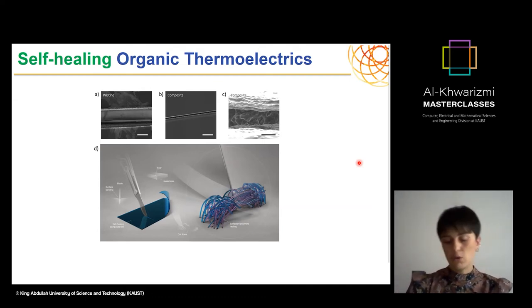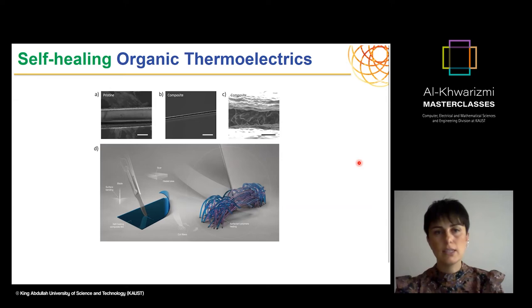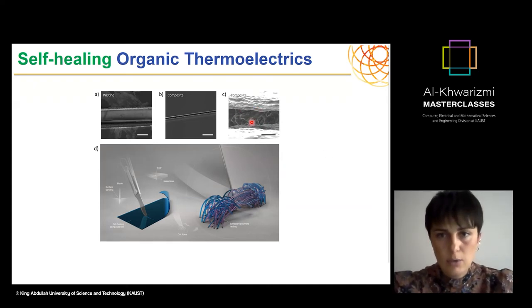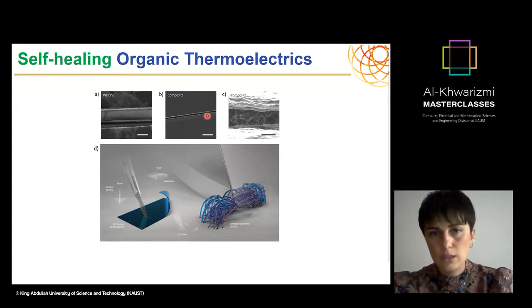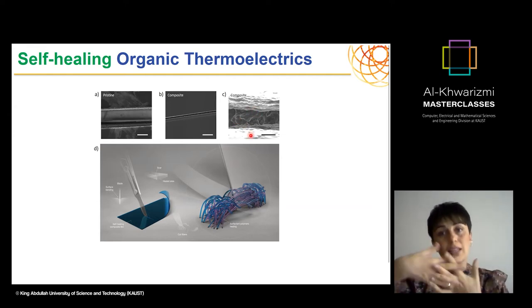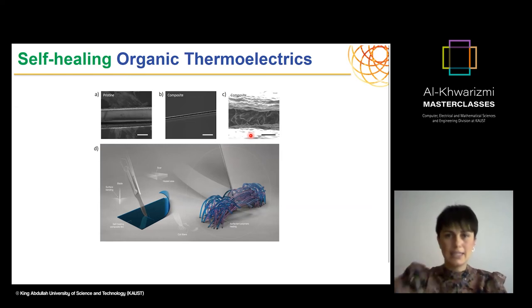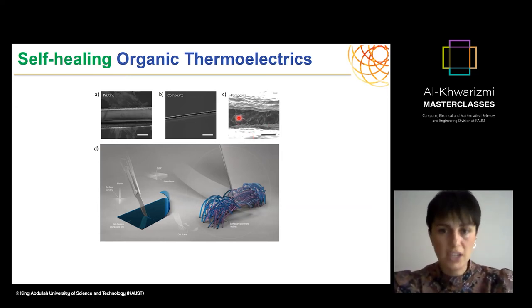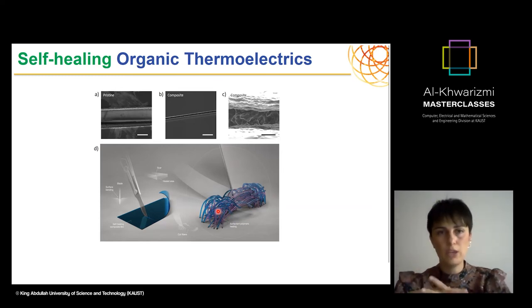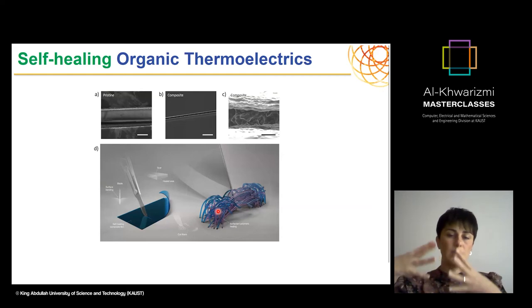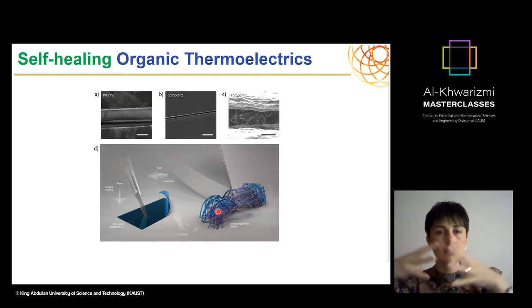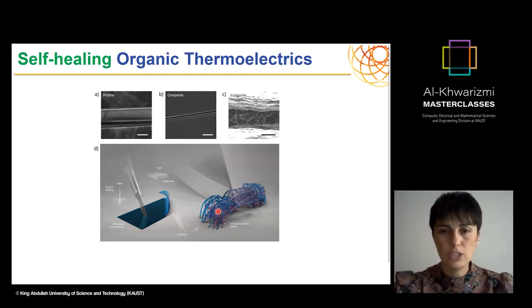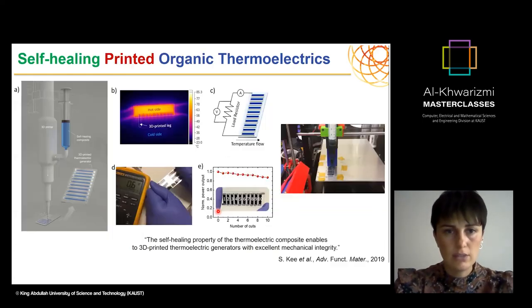And then we used some commercially available materials to start with. And in the end, here you see some of the SEM images. We had a huge cut and then looked into that. And we were still able to see that the self-healing material was in there, healed, let's say, and functioning. So this is our hypothesis that the self-healing material is bundled with the PEDOT molecule. And when you cut it, it supposedly heals back and then makes those polymer chains closer to each other again. And here are the results.